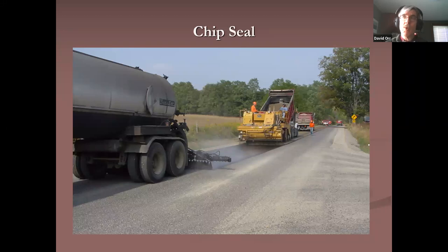I'm gonna take a risk with one here in a minute, but we'll see if it plays. But the thing I want you to do, if you're doing anything with a chip seal or a sand seal, that distributor truck with those fans, by the way, just like we saw in the old picture from over 100 years ago, and the distributor of the rocks, whether it's the distributor truck or the back end of the trucks themselves, keep that distance short, okay? Lynn Irwin always liked to say, I need to have a rope between the guy driving the distributor and the guy driving the spray truck so they didn't get too far apart, okay?